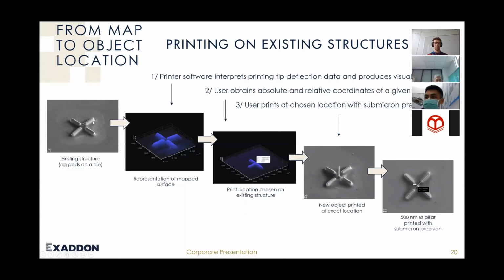To go through this example here, we have this cross structure on the left. The tip has interacted with it during this mapping workflow. We get this representation of the surface, which has been mapped, as you see in the second image. Then in the third one in the middle, we see the coordinates right in the middle of this existing structure. Choosing a print location, which is entirely down to the user, within this map that the software has generated, they can choose an extraordinarily precise print object location. And so we produce this micropillar in the center of the cross, which has a diameter of around 500 nanometers.